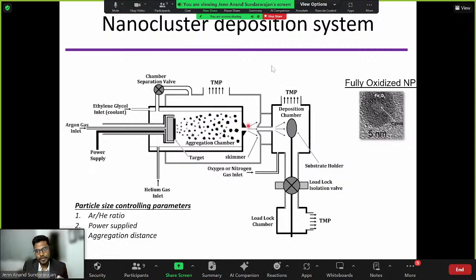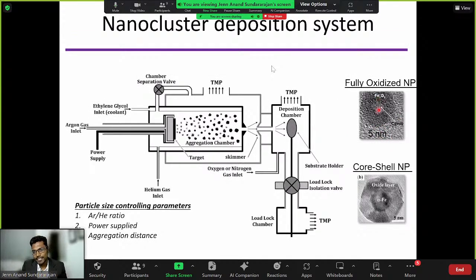But as they come and deposit here, what we do is we release some oxygen into this deposition chamber. And as oxygen comes into the deposition chamber, iron gets oxidized, right? And only the surface gets oxidized. Once the surface forms a protective layer, no oxygen can diffuse further. So it has a core, and now it also has a shell. But if the particles are too small, let's say 5 nanometers, as it oxidizes, the core also oxidizes and becomes a fully oxidized nanoparticle. So the answer to your question is the size of the nanoparticle. If it's too small, it will become a fully oxidized nanoparticle. But if it's enough size, then it can form a core-shell particle like this.